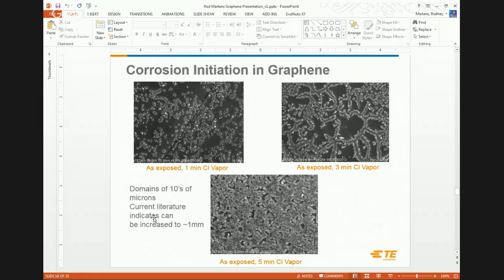But what you end up having is grain boundaries. And what we did here is we took a copper coupon that had a monolayer of graphene on it, and then exposed it to a chlorine vapor for 1, 3, and 5 minutes. And what you can start to see is a decoration of these grain boundaries. So this would be imperfections in the graphene.